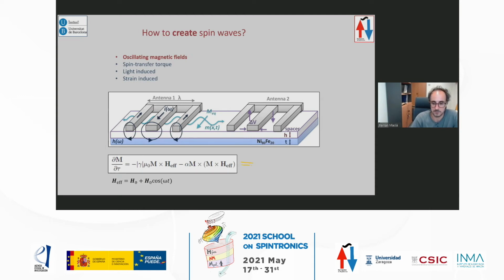So again, I wrote the Landau-Lifshitz equation, the equation of the dynamics of magnetization. And what we do here is create an effective field, a magnetic field that is oscillating. So it has a component that oscillates, and that means that you will have something oscillating here, also here, but now I'm not interested in that. That's going to create some dynamics in your moment. Okay? So then we can create some particular excitation on a thin film, and that could propagate. This is not very efficient, but this works very well, and it can be used to study films or to create devices. Of course, we need thin films. This is nickel, which has, let's say, good propagating distances, okay? Low damping in this case.